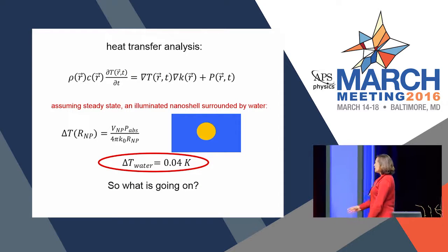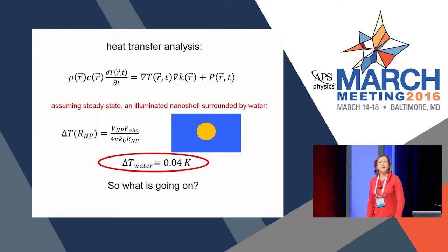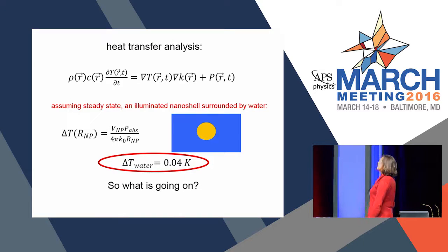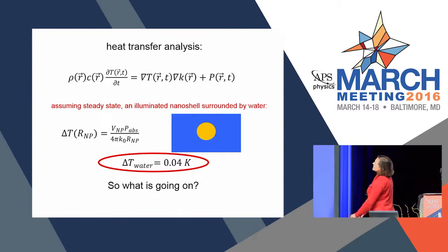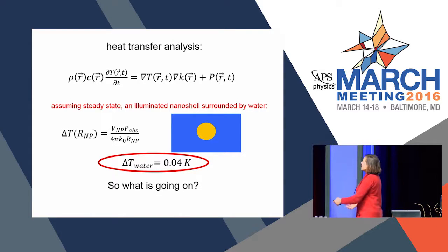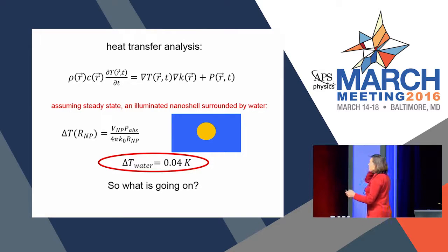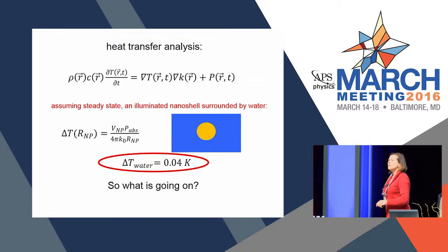So if we solve the heat transfer analysis, some of you might be feeling very uncomfortable at the moment as I describe this. And you wouldn't be the only one. If you just go and solve the standard heat transfer analysis, of course, what you're thinking is these are particles embedded in water. It's a water bath. The water has got to win, right? And if you just go through the numbers, you find that there should be no temperature increase at all, right? A minute temperature increase, like less than 1/10 of a degree. So what in the world is going on?